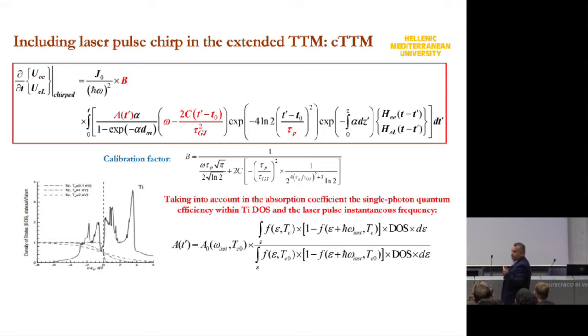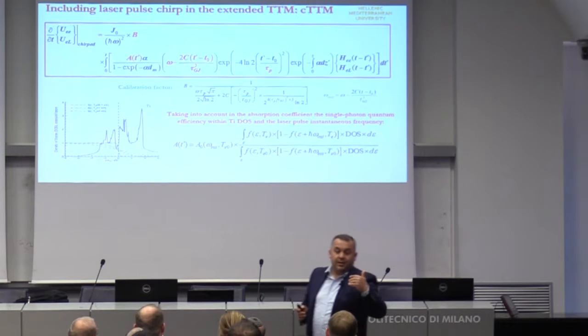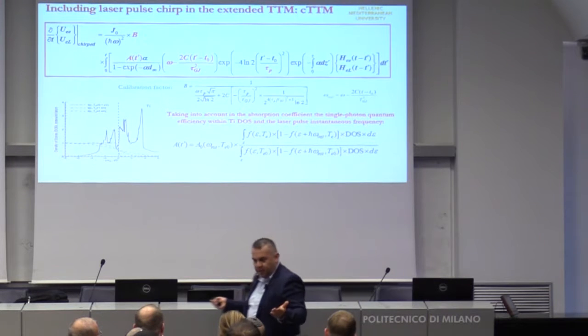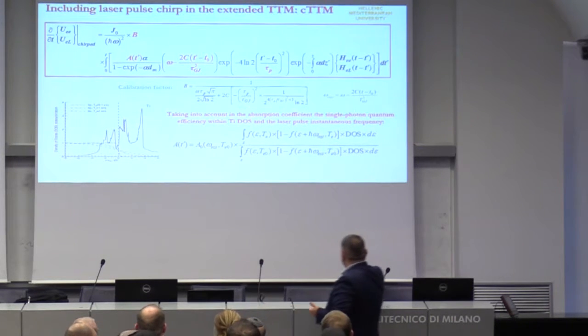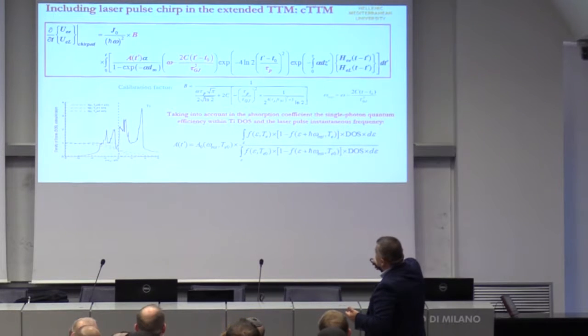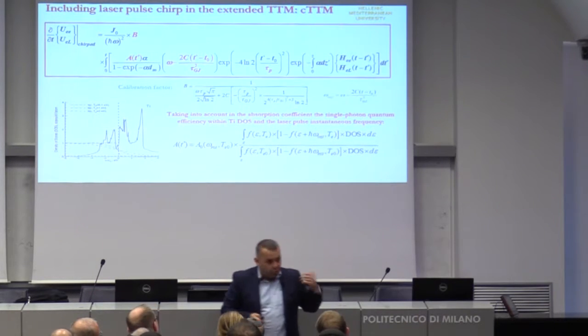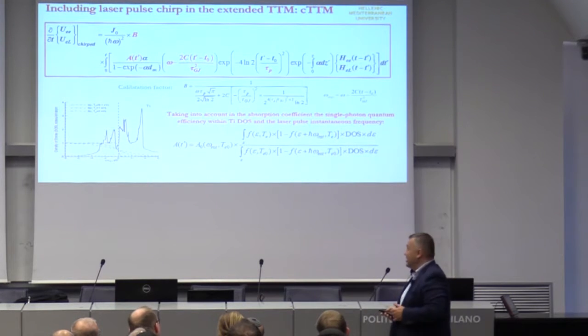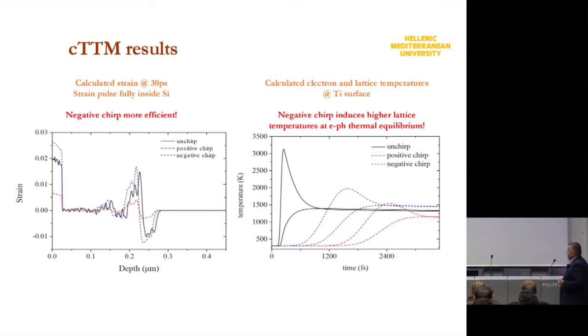For the first time, we have put the instantaneous frequency in the Anisimov equation. If you see the Anisimov equation and read some books, every time there is an envelope of a pulse. Never is the chirp put inside to calculate lattice temperature, electron temperature, and things like that. So here is the instantaneous frequency that we put in as a function of non-thermal electrons. We have also put the density of states of titanium, and we can actually calculate everything using these thermal equations, and these are the theoretical results.